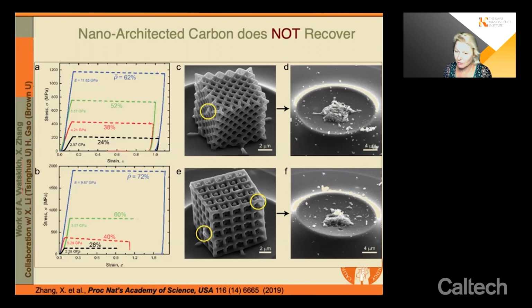In fact, the elastic buckling is not even available to them because there are so many defects, like flaws, small microvoids, inclusions and stress concentrations, that before your material ever has a chance to experience buckling as a structural response, the material itself fails at these local stress concentrations and failure propagates fully. And this is exactly what we've been observing. Now, if we were to make hollow nanolattices using thin ribbons of nano-sized carbon, and simply coat a scaffold and then etch it away, the same type of recoverability would not be possible.